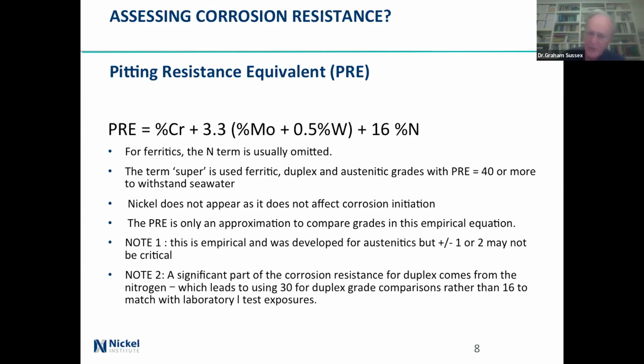A significant part of the corrosion resistance for duplex comes from the nitrogen, particularly for the lower alloy ones. So quite often you will see a 30 instead of a 16, because it was found that if you just used that PRE and then compared it with a chemical test, you got a lot worse results from this PRE number, as in it said, no, it won't work, but it did work quite well. And that's basically just, if the nitrogen is up, then you put up a higher ratio.